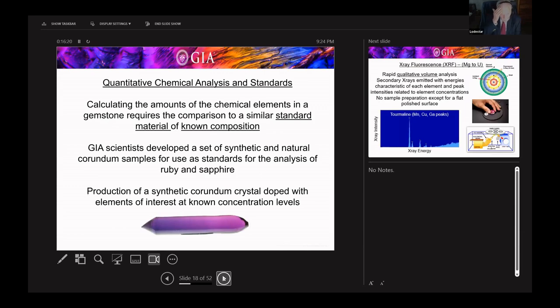If you're going to do a quantitative analysis and determine how much of the elements are present, you need to analyze a standard material of known origin, of known composition. Most of our analytical work on colored stones is on ruby and sapphire. So we have developed a set of synthetic and natural corundum samples for use as standards for the analysis of these important two stones. And by standard, I mean it contains elements of interest at known concentrations. So we analyze the gemstone and we analyze the standard. We know how much is present in the standard, and we can calculate how much of the minor elements are in the gemstone.